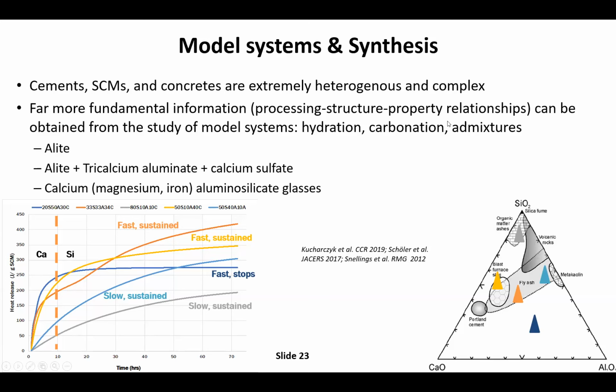There's far lesser study on SCM model systems. So as I mentioned to you, the calcium aluminum silicate glasses, you can actually synthesize these. The method we use to synthesize is just heat them and cool them. Not trying to mimic industrial practice, but that's how you can synthesize these materials. And then in one of our projects, we synthesized a bunch of materials. I'm not showing you all the data, but essentially we covered the calcium alumina silicate ternary diagram, not exactly a phase diagram. And then we also started doping it with magnesium and iron.